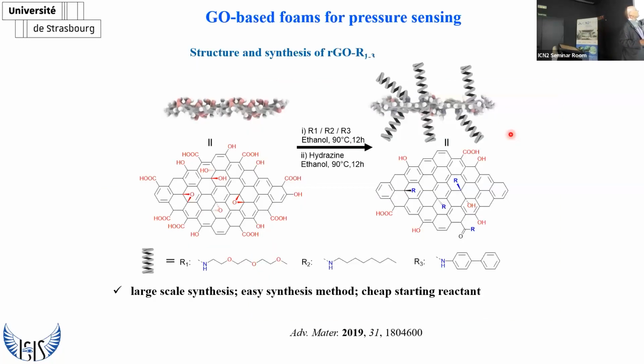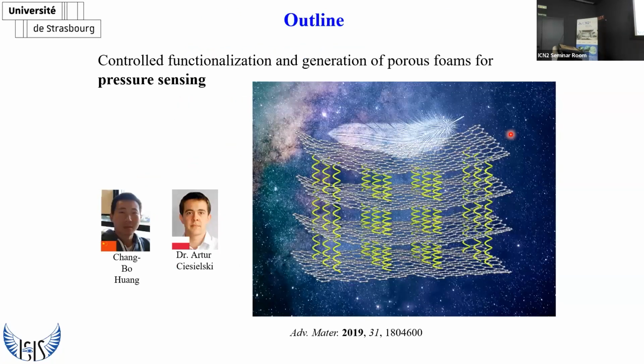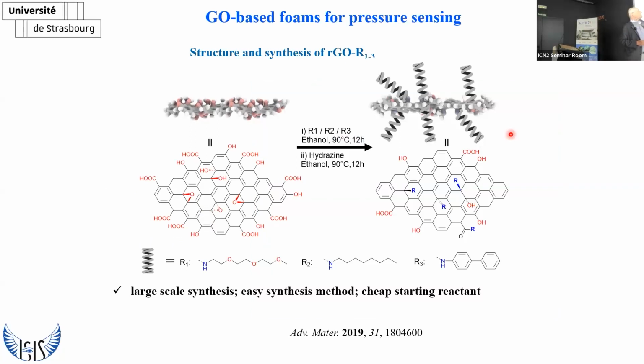And so the idea was pretty simple. We took GO, graphene oxide, and since we wanted to grow molecules edge-on, we decided to do a ring opening reaction. So we played with amino functionalized molecules, and we chose three different types with more or less the same contour length. One is ethylene glycol based, the center one is alkyl based, and the one on the right is biphenyl. In other words, we have a flexible, medium, and rigid type of molecule.